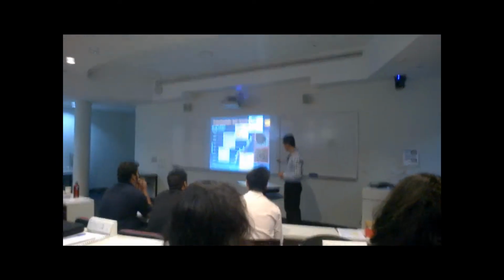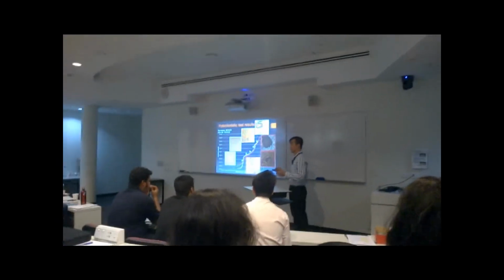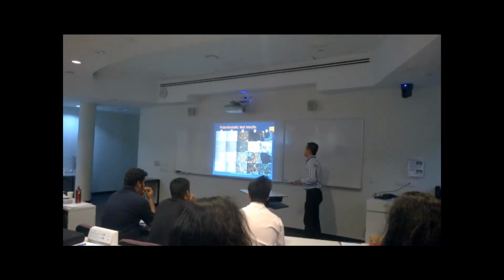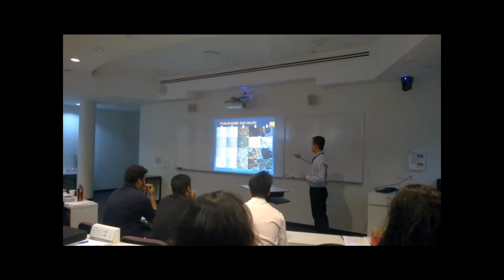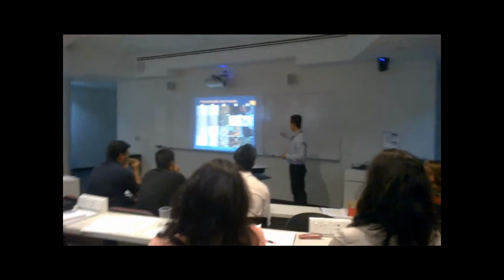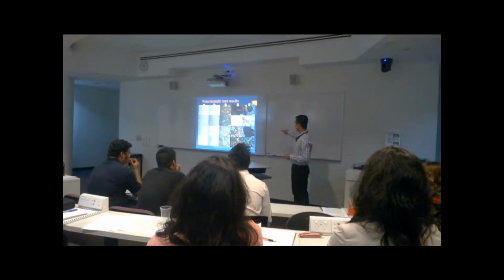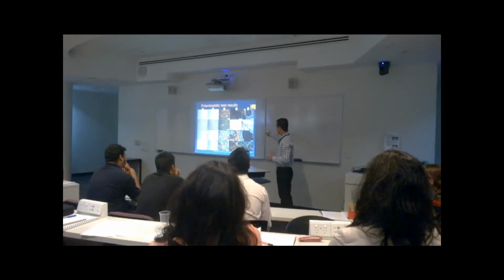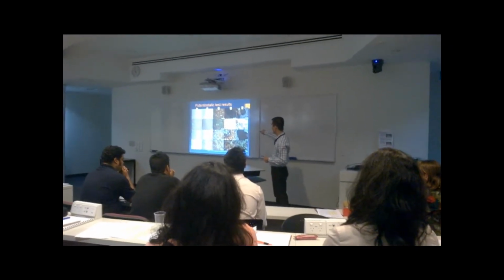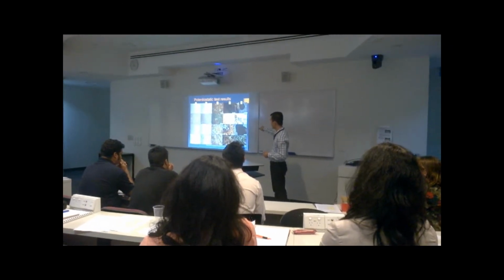Comparing the austenite and martensite matrix, martensite is more prone to corrosion compared to austenite, and that's the finding of my test. The next slide shows a summary of all the potentiostatic tests I have done on all my samples. From left to right is the microstructure of each alloy at 5 different potentials. I already showed you the microstructure change of B and 1B. B is the martensite matrix, and 1B is the austenite matrix, in the previous slide.